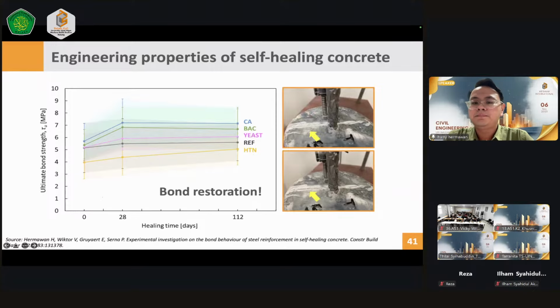But in addition to some proof that the self-healing is real, we can also evaluate whether there will be a bond restoration or not. Because we can imagine on our concrete specimen, if they have some cracking, of course there will be some reduction in mechanical properties. So from my research, fortunately we found there was a bond restoration after healing, especially after 28 days. If you see here, from day 0, which is after cracking, some of the mixtures underwent a partial bond restoration. However, above 28 days, for instance after 112 days, the bond strength after healing stays constant or remains stable.